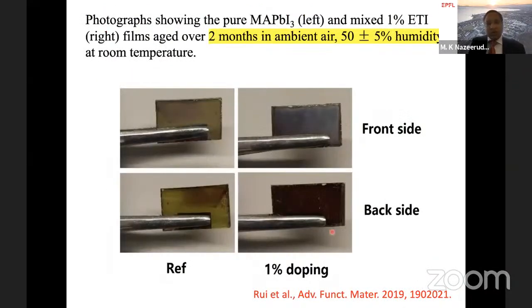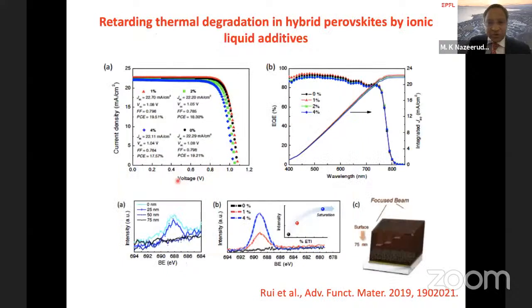And also, when we put these solar cells outside, with 1% of this ionic liquid inside the perovskite composition, for 2 months under ambient air with 50% humidity, the front side and back side under similar conditions, you can see the reference sample is decolorizing immediately, highlighting the performance characteristics of this 1% ionic liquid in the bulk perovskite material.